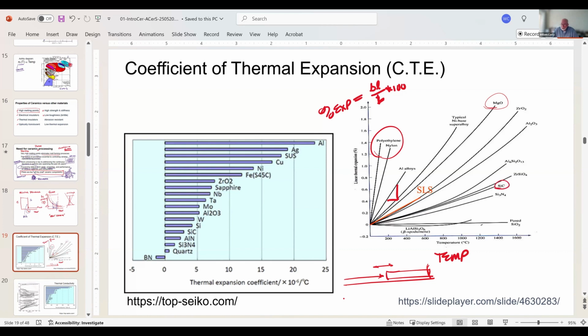And I go down here, silicon carbide, which is on my chart here, is coming in somewhere around 3. MgO is around 13, which is not on my chart, but it would be approximately here. So it's a huge difference in those materials, but not as huge as it would be for aluminum, which fits way up here. So here's my aluminum alloy, and then here is silicon carbide down here. So you get an idea. The lowest commonly produced material is fused silica, which is amorphous silica, and that has a thermal expansion coefficient of 0.5 times 10 to the minus 6 per degree Kelvin or per degree C. And that's this unit here, 10 to the minus 6 per degree C. So fused silica practically has no thermal expansion coefficient.